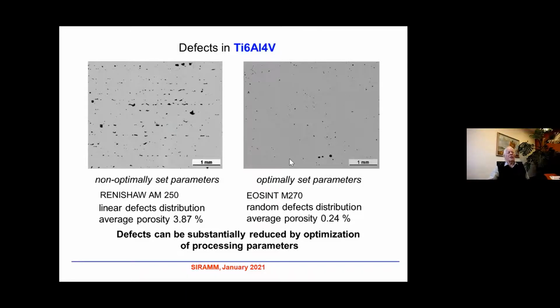On the other hand, on the right-hand side, you can see the microstructure of Ti-6Al-4V with optimally set parameters. This was produced on an EOSINT M270 machine. You can see the random defect distribution, and the average porosity decreased to 0.24%. So please remember that defects can be substantially reduced by optimization of processing parameters.